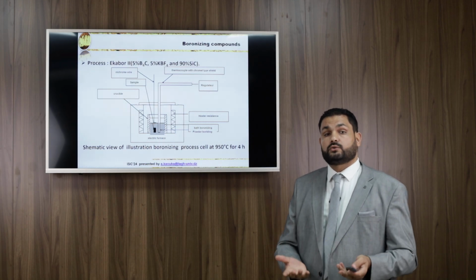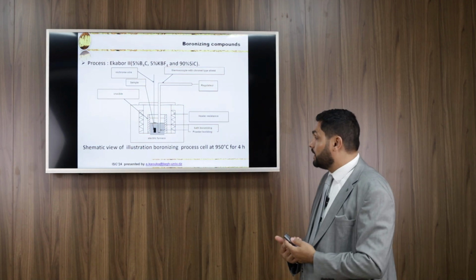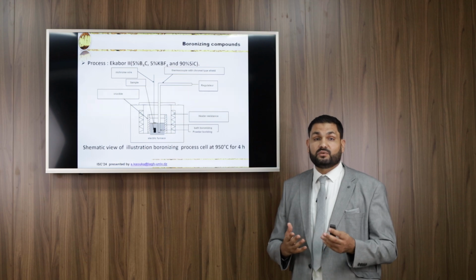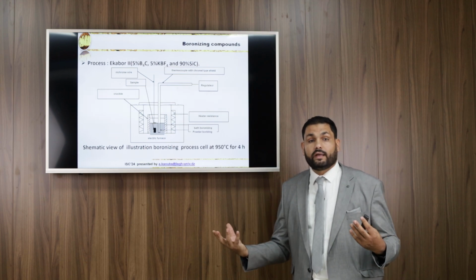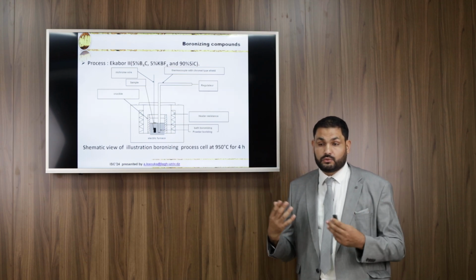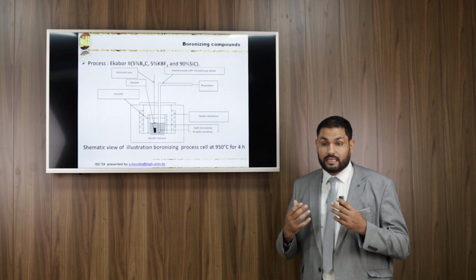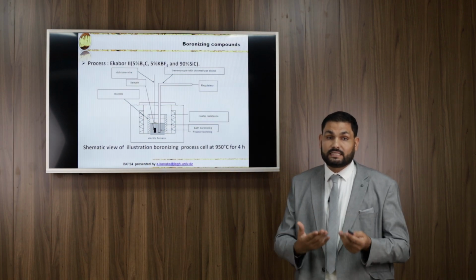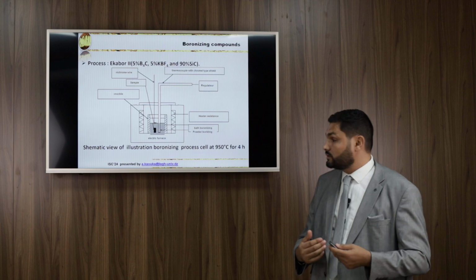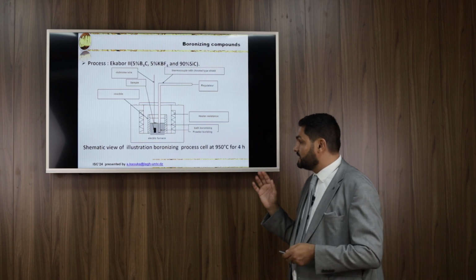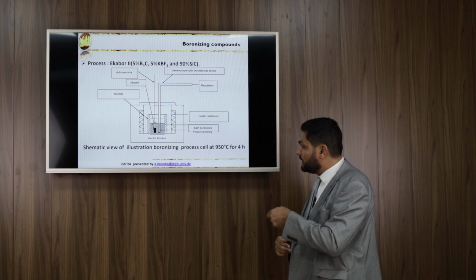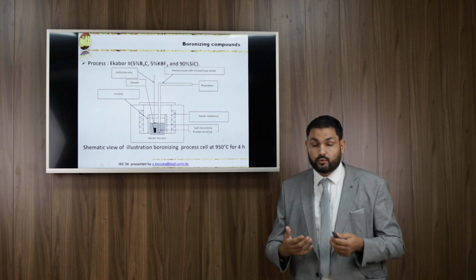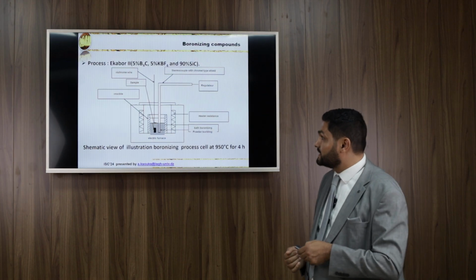We are not obliged to use a vacuum furnace. The temperature ranges between 800 and 1000 degrees for a few hours, between 2 and 8 hours. In our study, we chose 950 degrees Celsius for 4 hours. This is the optimal parameters, approved in our previous study.